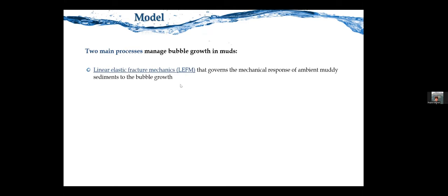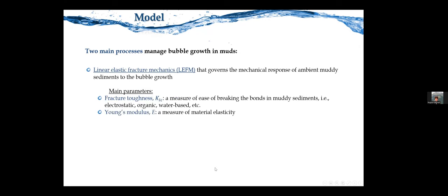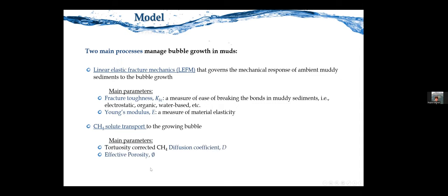The assumptions for the modeling are linear elastic fracture mechanics, which governs the mechanical response of sediment to the bubble growth. The main parameters, which are very important, are fracture toughness, a measure of the ease of breaking the bonds in muddy sediment, where the bonds are electrostatic, organic, water-based, and others, and the Young's modulus, a measure of material elasticity. The second main process is methane solute transport to the growing bubble. Main parameters are diffusion coefficient and effective porosity.